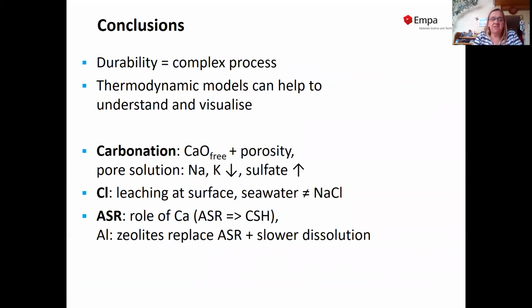So basically to conclude, durability is a complex process. Thermodynamic models can help to understand and visualize the processes. If we speak about carbonation, we can see that the free calcium oxide and the porosity are very important parameters. For pore solution, it's not only the pH that decreases, but also sodium and potassium concentration, while sulfate increases. Chloride, we observed leaching at the surface, and that there's a big difference between seawater and sodium chloride.